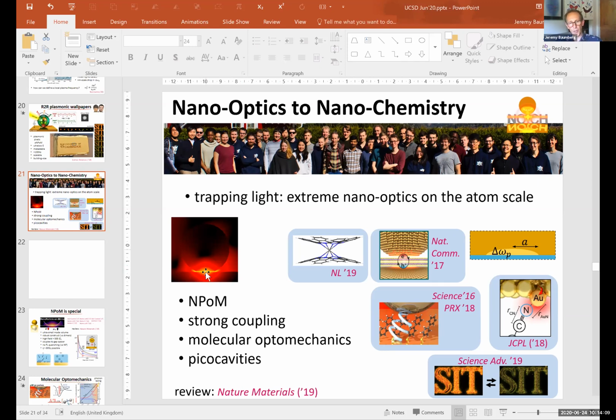When I take a cube on the mirror, because it's got a large facet, it's basically like what happens when the facet gets very large here. So the mode goes off into the infrared and then you can't get it resonant with the molecule that you want. So the difficulty is it's very hard to get a small gap with a cube that's resonant with the molecule. So you're going to have to do something else. That's the interesting challenge for all of you: try and figure out how you would do that. Okay. It's a good challenge.